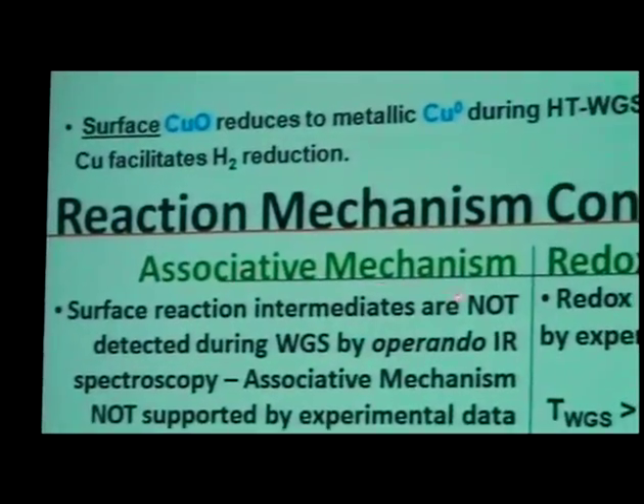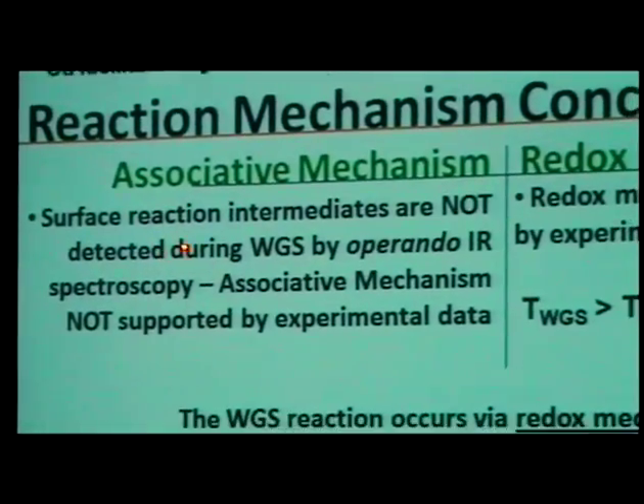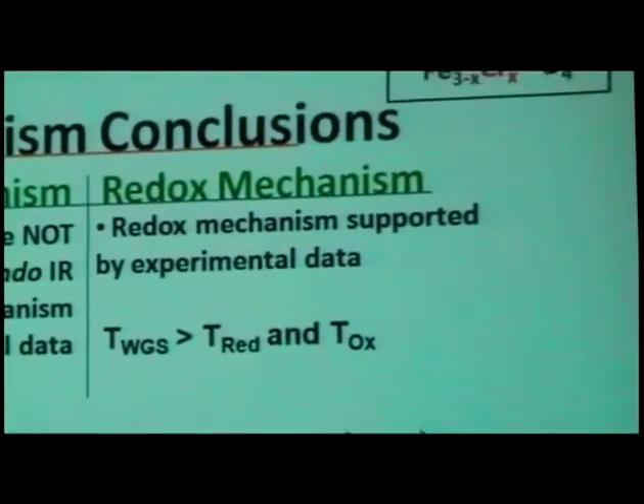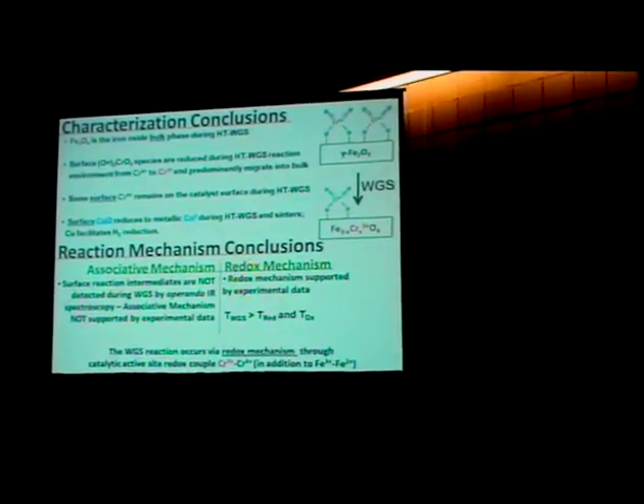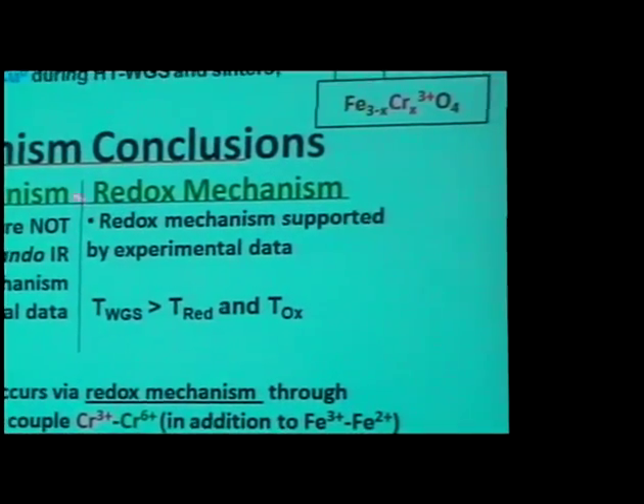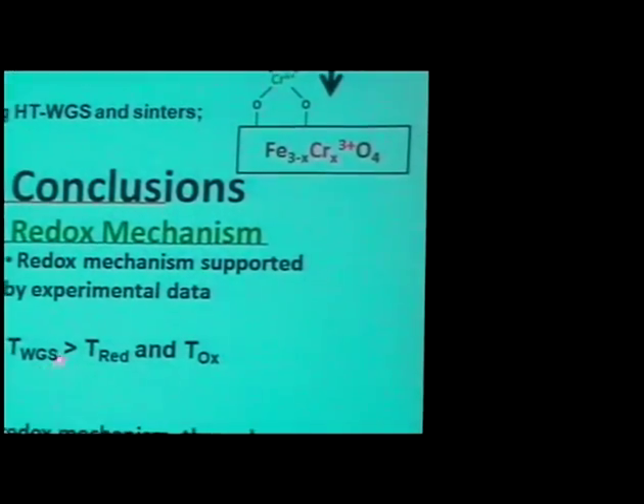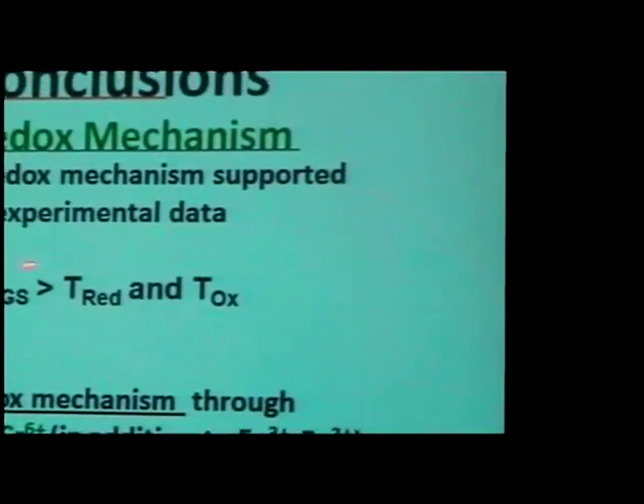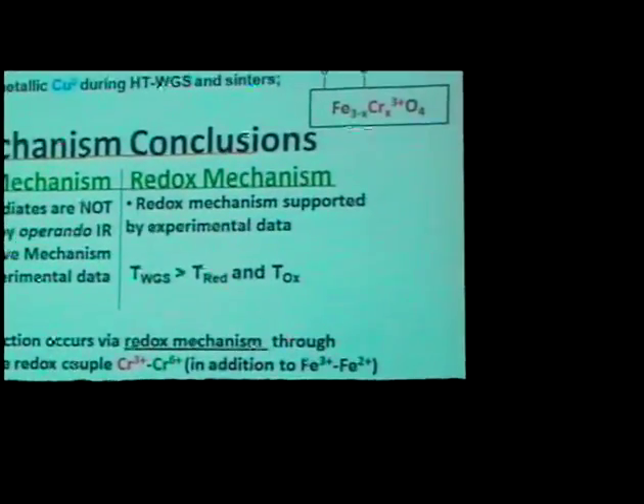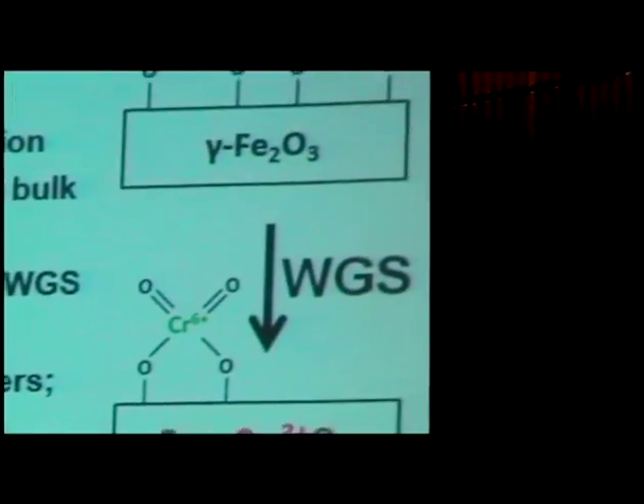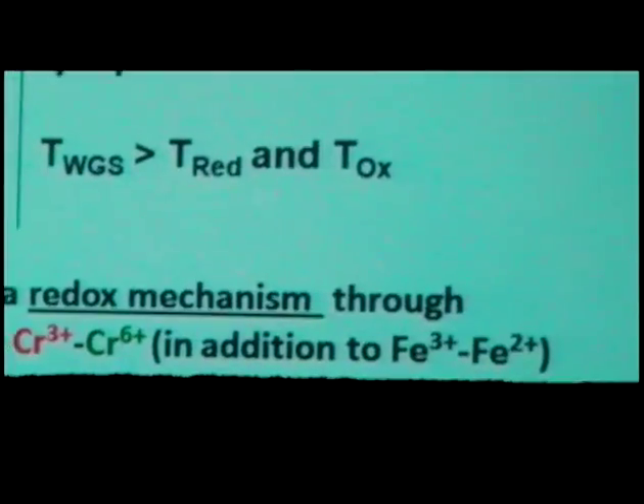As far as the reaction mechanisms, for the associative mechanism, not only do we not see formate forming on the surface during the gas shift, we do not see any surface intermediate whatsoever. And so even though this mechanism has been proposed by many people for many decades, no one provided any evidence to support the presence of surface formate. And in terms of the redox mechanism, indeed the catalyst is able to give up oxygen and reoxidize, give up oxygen to CO2, oxidize water, at temperatures where both the reduction and oxidation temperature are lower than the water gas shift, indicating that this appears to be a feasible mechanism for this reaction. And we'd like to further propose that since there is some residual chromium-6, which is very easy to reduce, this chromium-6/chromium-3 redox couple is responsible for this redox mechanism of these water gas shift catalysts.